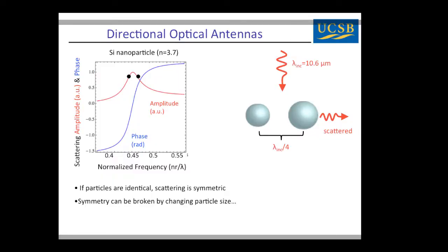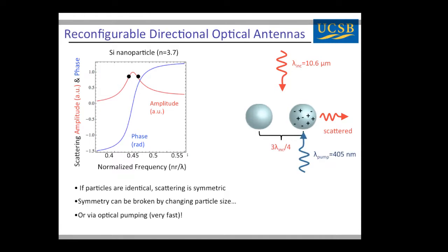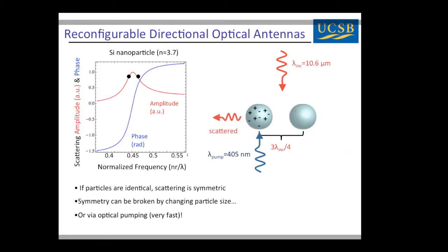Okay, now as I mentioned, what we're interested in doing is doing this in a reconfigurable fashion. So rather than changing the size, the idea we want to look at is whether we can mimic the effect of changing the size by changing the refractive index. Okay? So what I'll be looking at is how the response of these antennas changes as we introduce free carriers into the semiconductor. Okay? So this could be done electrically or, as shown up here, optically. For now, let's not worry too much about how we get the carriers in. We're just going to do some calculations where we imagine what happens as we introduce free carriers. Okay, so again, the idea now is it's reconfigurable because if we introduce them to the left, we get a diffraction lobe to the left instead of to the right.